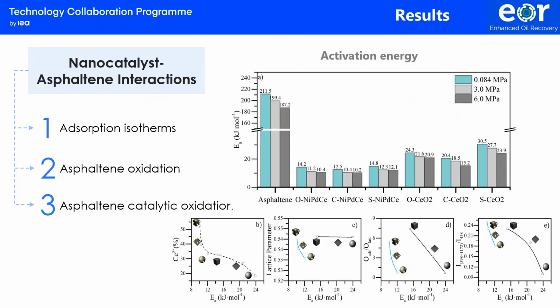As for the effective activation energy, it is reduced when the nanocatalyst presented a cubic shape, followed by the orthorhombic and the spherical. Besides, the presence of nickel and palladium phases reduce the activation energy values. The results also highlight the obvious effect of the exposed ceria crystal planes, the redox cycle, the content of oxygen vacancies, and the strongest interactions between the nickel and palladium species and the support on the asphaltene oxidation.